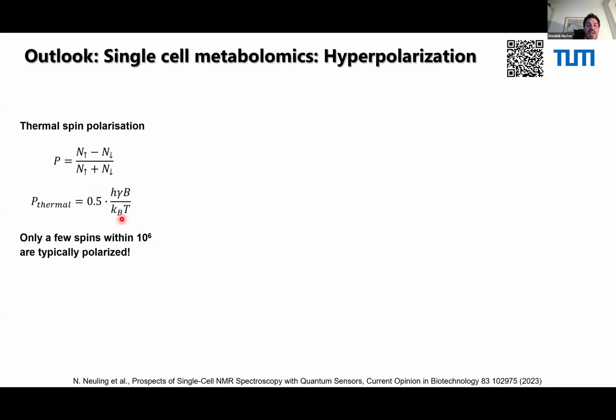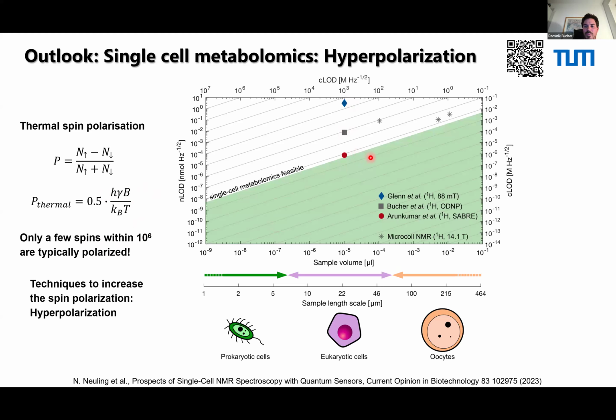Tesla at room temperature. But there are techniques which we call hyperpolarization, where we can now increase this number up to a few percent or a few 10% in some cases even. And also this we have partly shown during my postdoc time. We use the technique where we use para-hydrogen, so you can easily go down here.